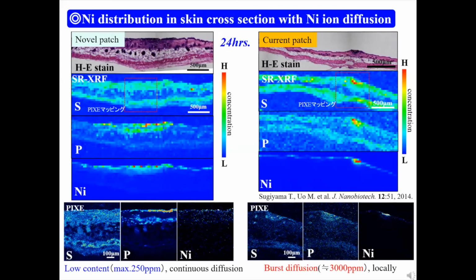This slide shows the comparison of nickel ion penetration into skin from the novel nanoball patch and the conventional nickel sulfate solution patch. In the conventional patch, high-content nickel solution is directly applied to the skin. Then, the nickel ion was localized just beneath the point where the patch was applied. Then, an acute skin reaction occurred.